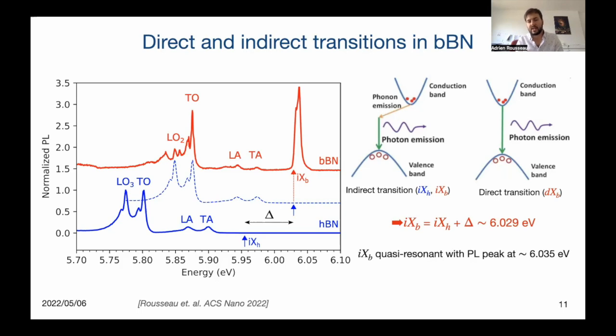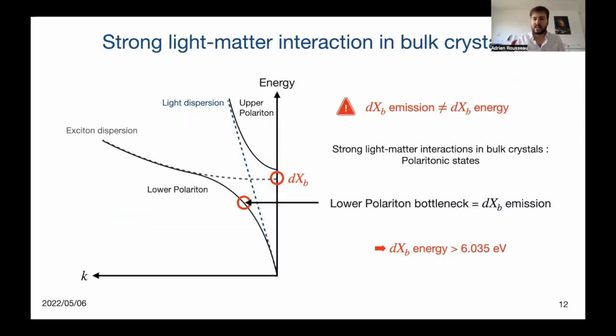The energy of the indirect exciton in Bernal boron nitride is represented by the red arrow on the figure on the left. We then observe that the indirect exciton in Bernal boron nitride is almost resonant with the direct transition at 6.035 electron volt. Nonetheless, it should be noticed that the energy of the direct transition in Bernal boron nitride is different from the energy of the direct exciton because of the strong light-matter interaction which appears in bulk crystals, forming polaritonic states.